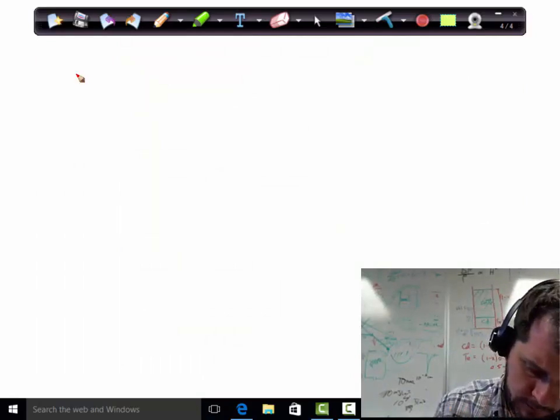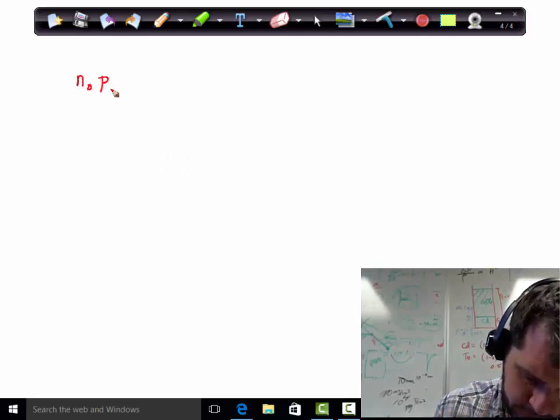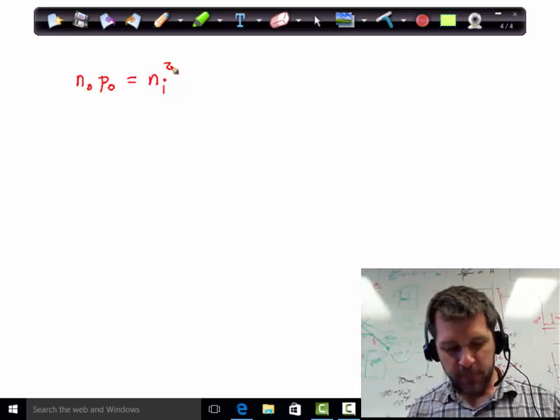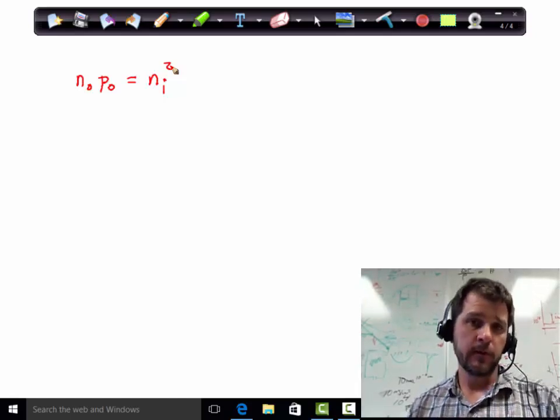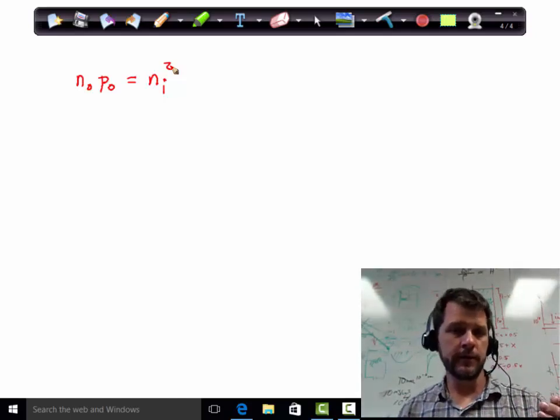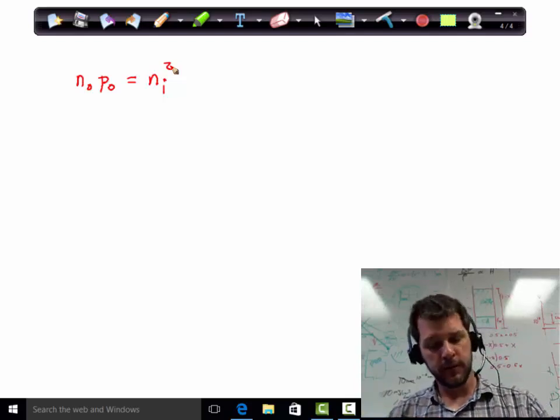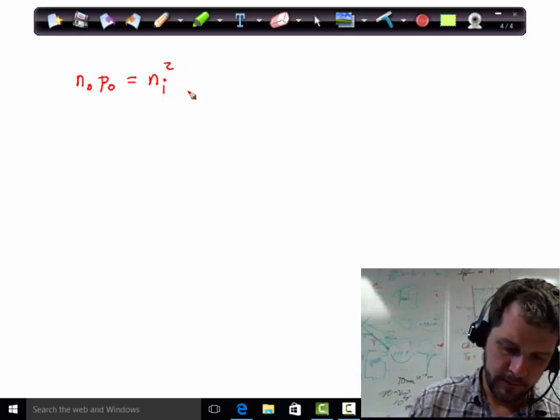There's a very compact expression that's really the expression of a rate equation, or a dynamic equilibrium equation, and it's simply that the product of electrons and holes in a semiconductor, whether it's intrinsic or whether it's doped, will always equal Ni squared.